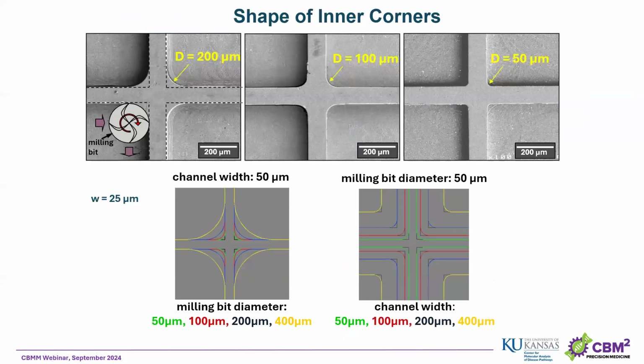The other limit is that the cutting tool is round, right? So it cuts round. If you try to cut a round corner, the smallest diameter that you could cut will be the same as the diameter of your milling bit. So let's say you would like to cut this cross pattern. You're milling your metal master with the 200 micrometer milling bit. Then you will have this curvature, right? So your ideal geometry will be those really sharp right angles, but you will still have some rounding just because of the milling bit geometry, right?